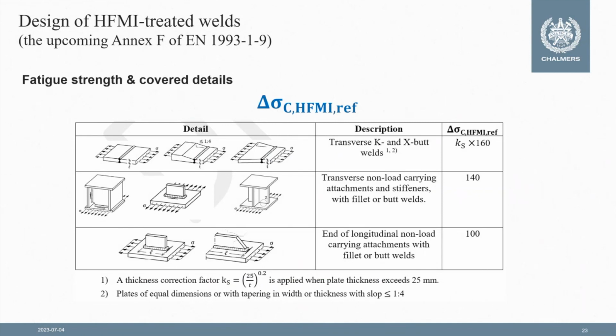In the current version or the upcoming version of Eurocode in Annex F, there are in principle these three details that are covered: transverse butt welds, transversal attachment, non-load carrying attachments similar to vertical stiffeners and plate girders, and longitudinal attachments. And for each of these three details, a detail category, the reference delta sigma C HFMI is given. So either 160, 140, or 100, and you see directly that we are leveling up the fatigue strength. For example, for transverse attachment, it's 71 or 80, depending on the thickness of the attachment. And we are leveling this up to 140, which is very close to the base metal fatigue strength. But this is the reference value for the fatigue strength.